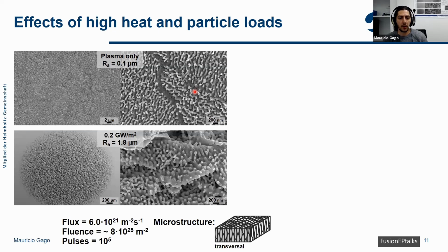Then once 100,000 laser pulses were applied of 0.2 gigawatts per square meter, we can already observe here that there are cracks being formed and the surface has been roughened. And we still see some of the tungsten fuzz being formed here. Also the roughness of the surface. We can see here that previously it was much lower than when the laser pulses were applied. And we can see the laser spot here very clearly. And outside the laser spot, the surface was actually not really affected that much.